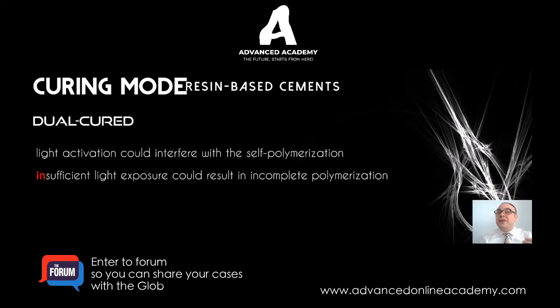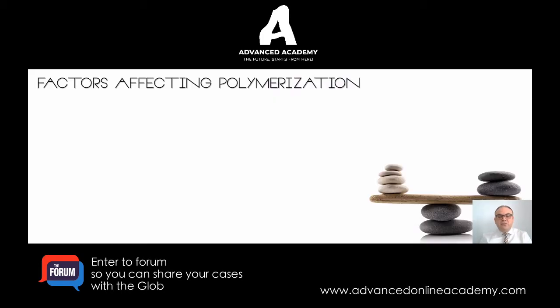If you don't have water penetrating through the material, that's also going to compromise the efficiency of these cements. And so we want to delay the light activation as much as possible, between 2 to 5 minutes. Now, you saw that this is a delicate process. The polymerization process was delicate, going from low pH hydrophilic to increasing in pH and becoming hydrophobic. So what are the factors that can affect this polymerization process?